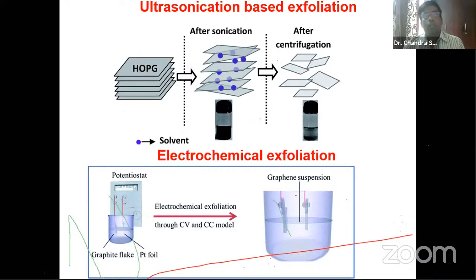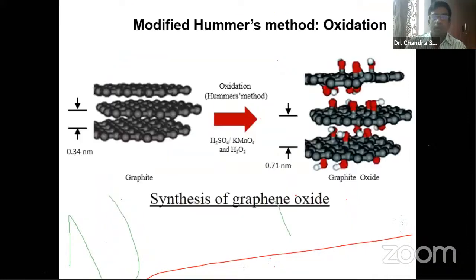This is another approach in which they use electrochemistry, like you have a cathode, an anode, and then use graphite, and the graphite is exfoliated to form few layer or single layer graphene. So this is the chemical method. It is widely known as Hummers' method because Hummers first discovered this approach. This is the chemical oxidation method. They use an oxidizing agent like potassium permanganate, H2SO4 acid, and H2O2 to exfoliate the bulk graphite, to achieve single layer or bilayer. Single layer is a little difficult to achieve by this method. Usually, few layer graphene sheets they achieve.